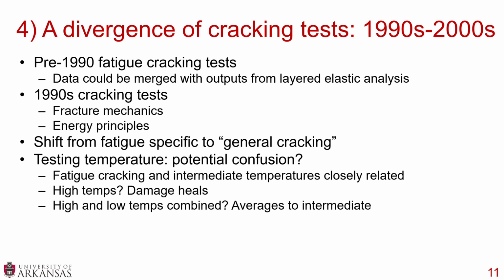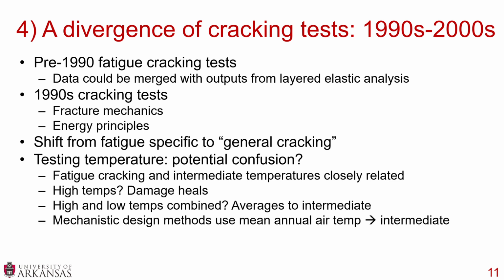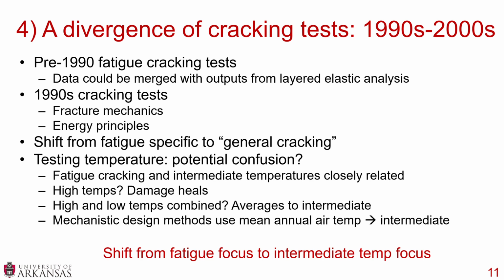Other reasons were at high temperatures, the damage healed, so any sort of high temperature cracking, you really didn't see anything. If you did start thinking about high temperature cracking, you also start looking at low temperature cracking. If you combine those temperatures, it averages to those intermediate temperatures. And the mechanistic design methods use mean annual air temperature which are intermediate temperatures. So what's happening here is in the 1990s, we're thinking about cracking tests. We're thinking about intermediate temperatures. So we're really seeing a shift from fatigue focus to intermediate temperature focus.